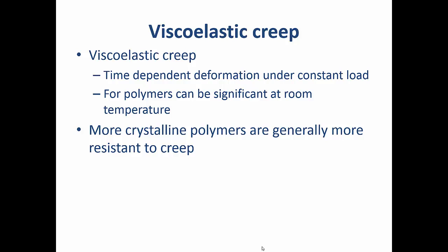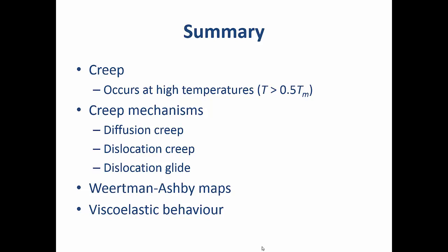You can also get viscoelastic creep, which is time-dependent deformation under constant load, and for polymers that can actually be very significant at room temperature. More crystalline polymers are generally more resistant to creep. So I've only really touched on the viscoelastic behaviour there.